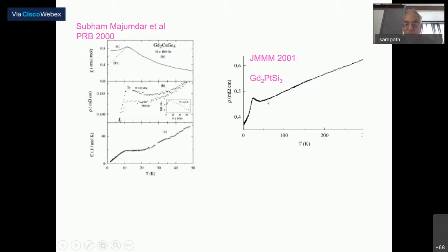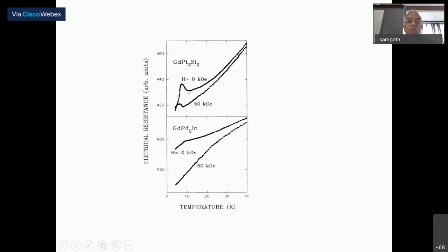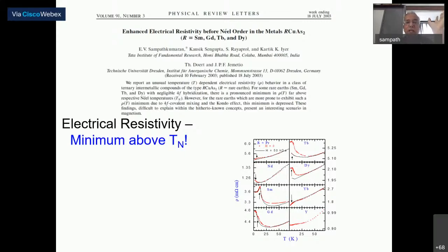This crystal structure is the same as that of the Gd2PtSi3. This is another crystal structure, a layered compound. Even here you find a minimum. There are some more compounds. The magnetoresistance is quite large, though you don't see a minimum here. So there is an additional contribution coming up in this family. Subsequently, by the way, even for arsenides, very famous, we studied a good number of arsenides. And this is another arsenide with a layered structure. We published it in PRL, not only on gadolinium.